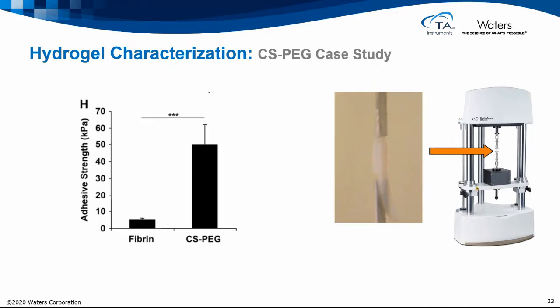Okay, and then finally, this is a simple plot, but it shows significantly better adhesive strength. This is really the goal of this hydrogel development: to create a better adhesive. And that adhesive now shows an order of magnitude increase in adhesive strength. This is done by what's called a lap shear test, where you have one material. I think they used cartilage on the top and cartilage on the bottom, and then you overlap them and bond those two materials together with this adhesive.